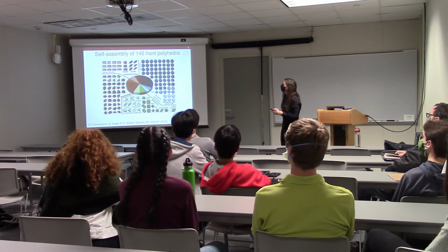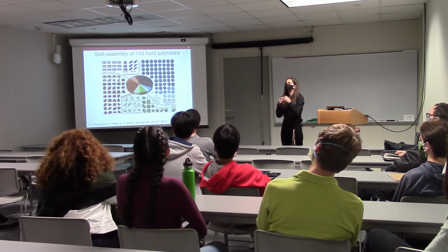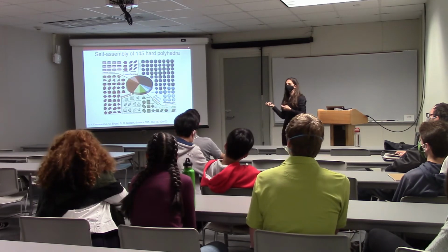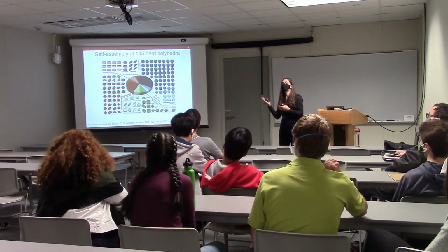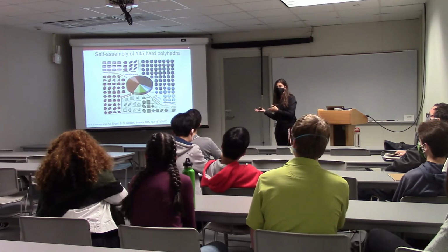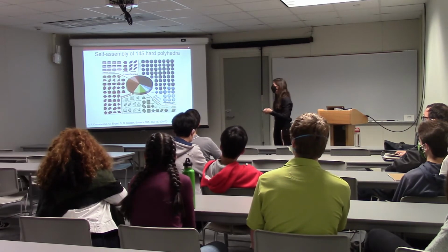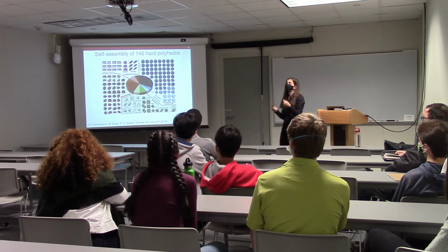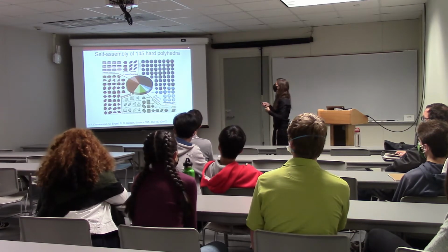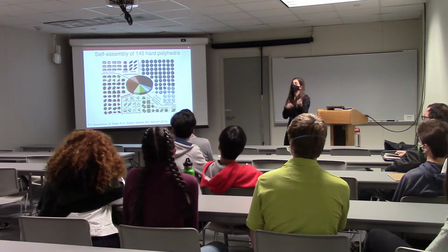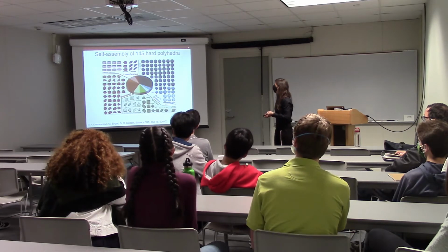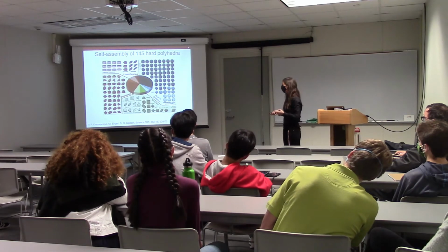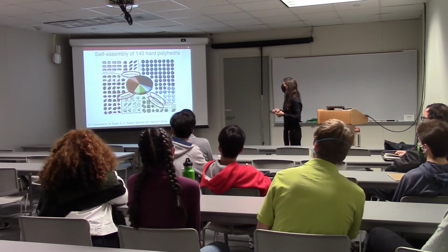I'm not going to talk much about quasicrystals, which is why I didn't bring you a quasicrystal primer, apart from my words. Basically, they then went on, like, we can do this with all the shapes, and did 145 different polyhedra, and it turns out not all of them are quite as crazy as tetrahedra. Tetrahedra are kind of the pinnacle of complexity, I would say, and a bunch of them are quite boring and disordered. Several are liquid crystals, so they're orientationally ordered, but not positionally ordered. Some are plastic crystals, so positionally ordered, but not orientationally ordered. And then down here you have a proper assortment of nice crystal structures that are just formed by their different particle shapes.